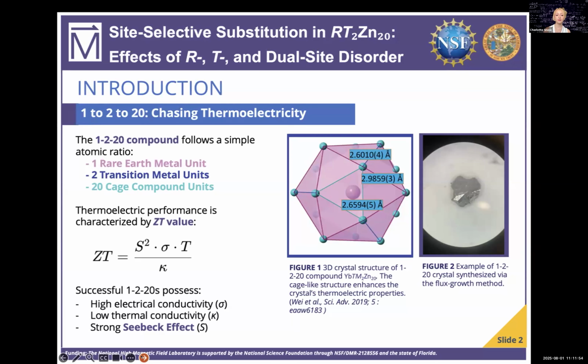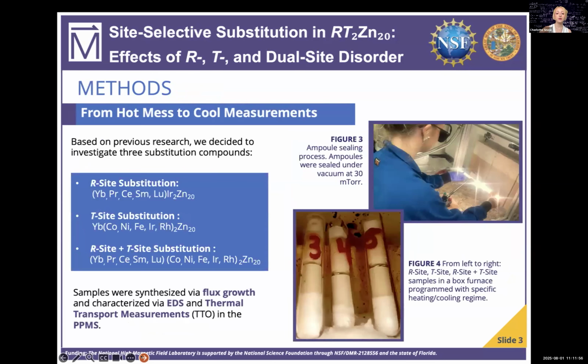So to test our idea, we introduced controlled chemical substitutions at different atomic sites on the RT2 zinc 20 structure, on the R or rare earth metal site, the T or transition metal site, and in one case, both at the same time. We wanted to see how disrupting the crystal's chemical order would affect its properties like we've seen in past research.